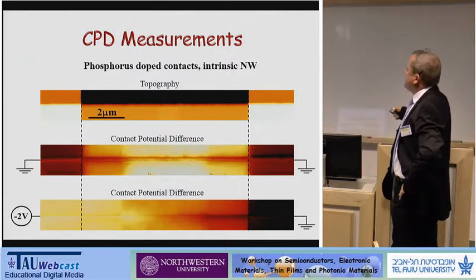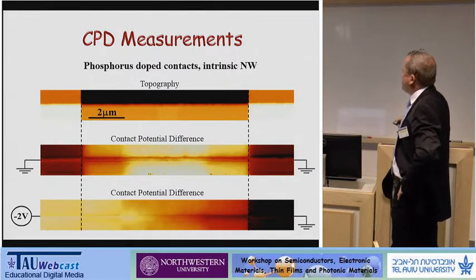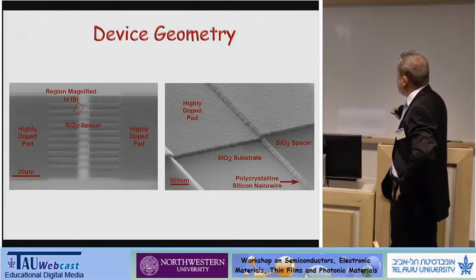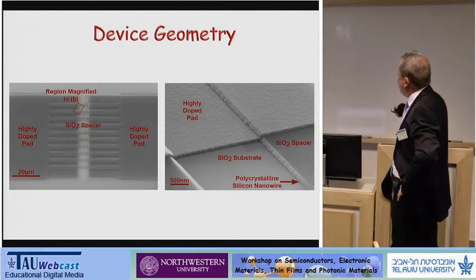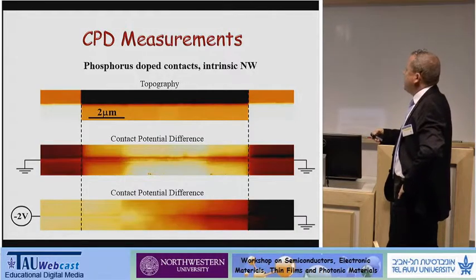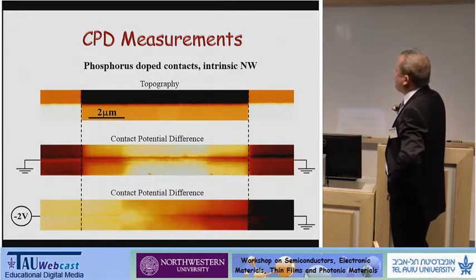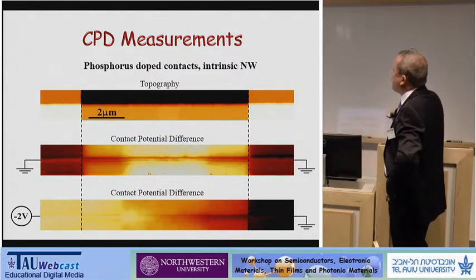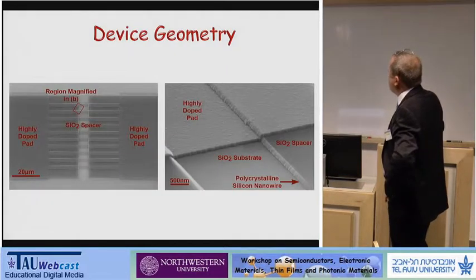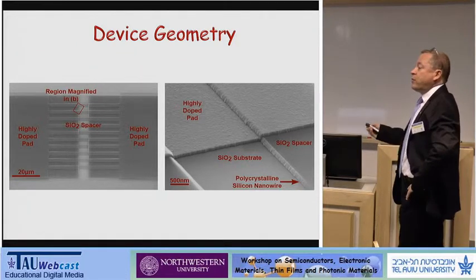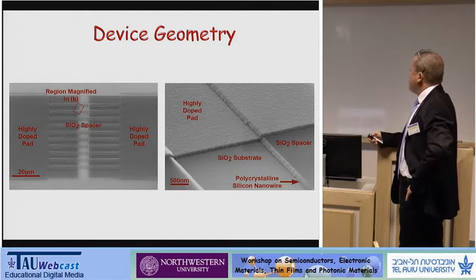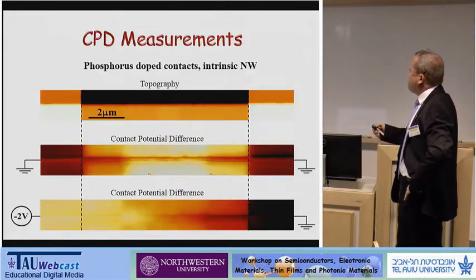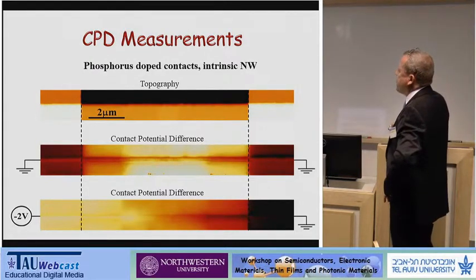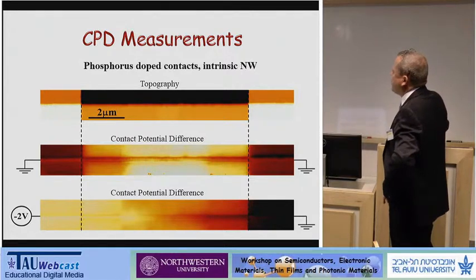What you see here is a measurement of one wire. I'll show you in the next slide a KPFM and topography measurement along a single nanowire. If you look carefully, this is the topography, and in the topography you don't see the nanowire very clearly, because you measure the topography across here and you cannot distinguish the nanowire very clearly from the silicon oxide spacer. But if you measure the contact potential difference, since the work function is different, you can clearly distinguish the nanowire.